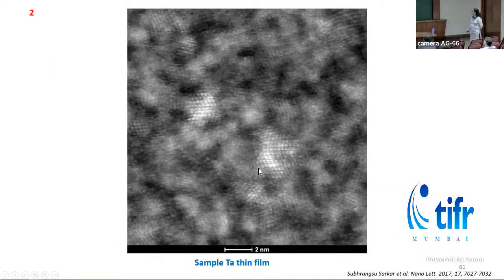This is again an example of tantalum thin film prepared by magnetron sputtering. Here different sizes of crystallites were prepared. This is the smallest crystallite, about 2 nanometers, prepared by using magnetron sputtering. So this is a single grain, or single crystal, of alpha tantalum. And here the question they addressed was, is there any lower limit to the crystallite size on superconductivity? So this was a very crucial image for this kind of work.